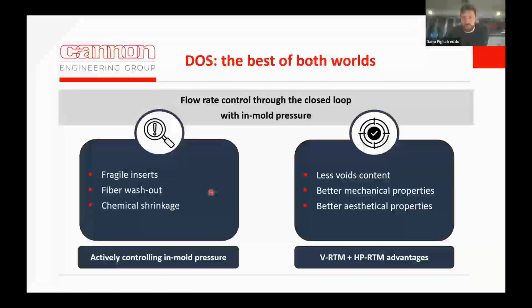To summarize what we said until now, we are able to combine the advantages of both HPRTM and vacuum RTM because our target is to actively control the pressure inside the mold by changing the flow rate. Our target is to be able to manage fragile inserts. We want to avoid fiber washout, and we want to compensate for chemical shrinkage after the injection is finished. Then we reach, of course, as an objective, less void contents.